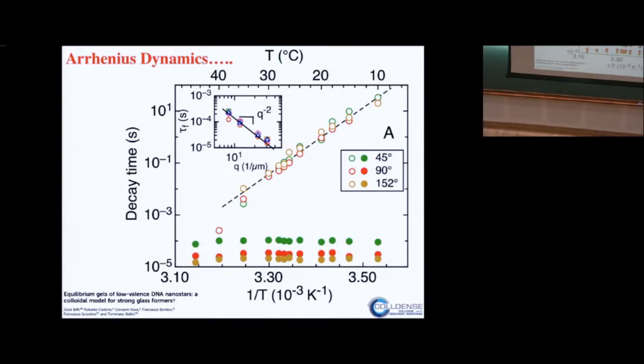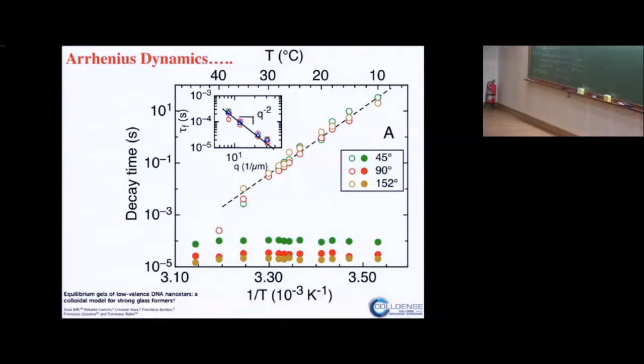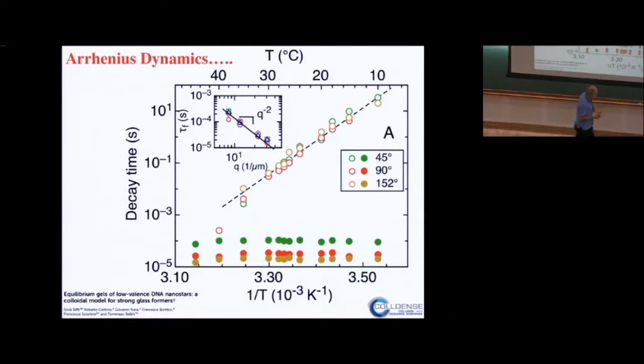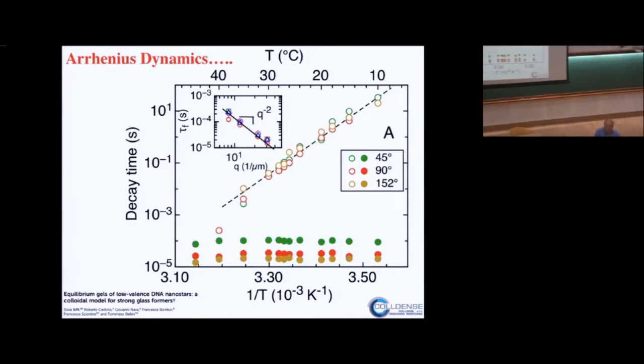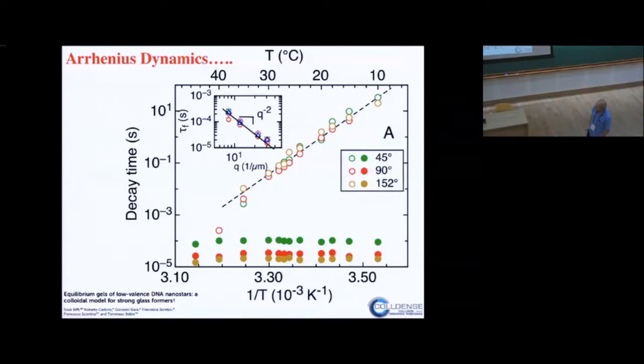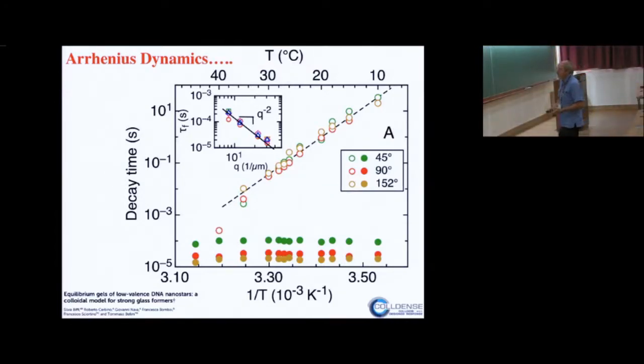Again, it's not a coincidence. All of them are limited valence systems. In all of them, the lifetime of the bond is controlled by the energy of the bond. That's the only relevant energy scale. It's different from the case of hard spheres or glasses, in which the activation energy changes with temperature.